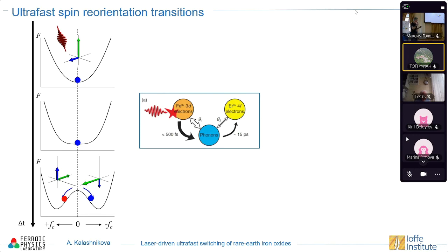Our idea is the following. If we have linear polarized light, this is our low temperature phase. This is the potential energy profile. So we're in the minimum. Then we have excitation, we have ultrafast heating, and after several picoseconds, two potential minima emerge, and magnetization, our system, can go to this minimum or to this minimum.